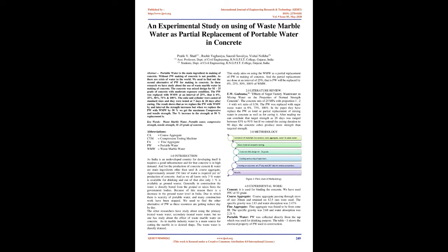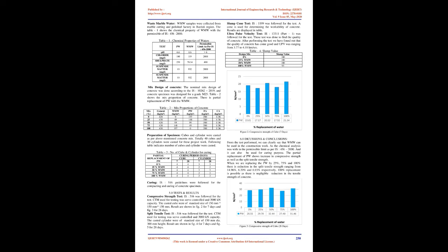2.0 Literature Review. E.W. Gadzama et al., effects of sugar factory wastewater as mixing water on the properties of normal strength concrete. The concrete mix of 25 MPa with proportion 1:2:4 with a W/C ratio of 0.56. The PW was replaced with sugar wastewater at 0%, 75%, 100%. In the paper they replaced the PW as total or partial replacement of mixing water in concrete as well as for curing it. After reading we can conclude that the 28-day target strength ranged between 83% and 91%, but if we extend the curing duration to 90 days the concrete cubes produce more strength than the targeted strength. 3.0 Methodology. Figure 1, flow chart of methodology.